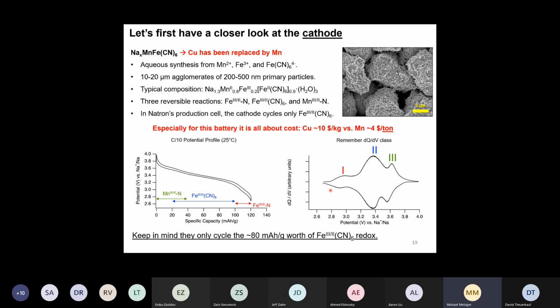If you plot this as a differential capacity, dQ/dV versus the voltage, you can see these redox features more clearly, and you can see that this middle redox is associated with the iron 2+, 3+.